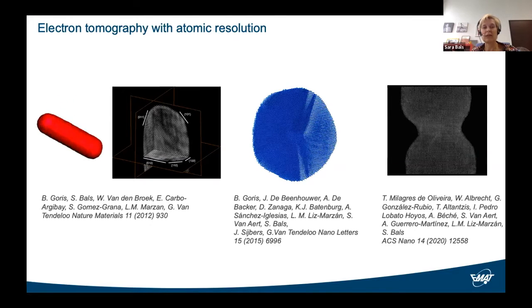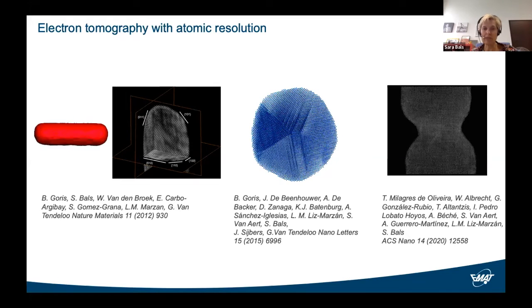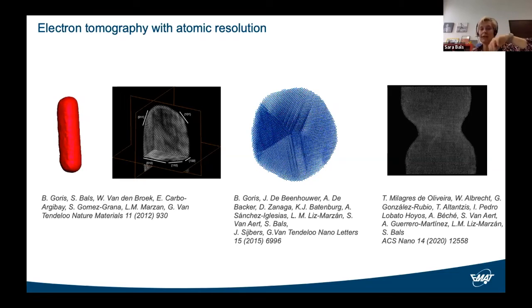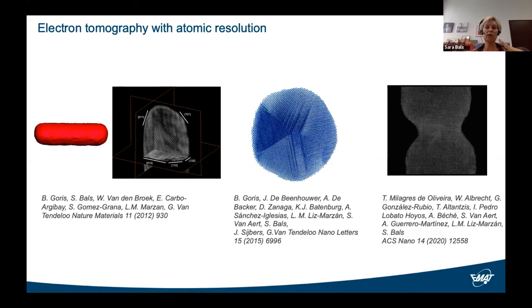And what we did is we exploited sparsity at the atomic scale, but more recently, by improving the acquisition and also the alignment of the tilt series, there is no longer a need to do so. And so all the way on the right, you can see a slice through a three-dimensional reconstruction. Again, two nanorods, and now they are welded together because of a femtosecond laser irradiation. And since we are no longer using any prior information, it is really nice that we can pick up individual defects, such as these dislocations here. And then we could link that to the properties of these systems, as we could see in the plasmon peak, a significant broadening.